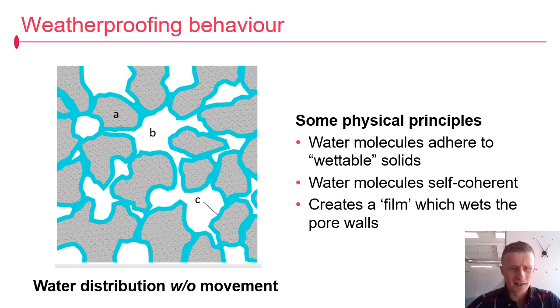So what you've got on the left is an idealised random cross-section for a porous material. The grey bit is the solid phase, the white bit is the pore, and the blue bit is the water. Now, some physical principles. Water molecules adhere to the walls of wettable solid surfaces. Okay, so that's like little magnetic marbles sticking to the wall of the pores. Now, if those marbles also were attracted together, then you're looking at water molecules, so they're self-coherent, they're attracted to one another as well. Those two physical principles compete, and if you chuck a bucket of water on a block of dry sandstone, you'll find that the water tries to wet as much internal surface area as it can, so that's adhesion, whilst maintaining intermolecular connectivity, so cohesion.